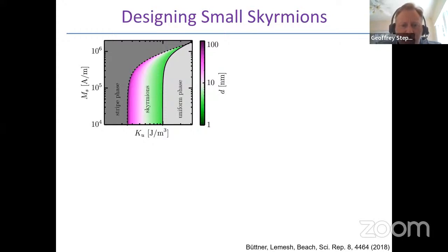So if one wants to improve the behavior and really push skyrmions down to a limit of 10 nanometers or less, that would make them desirable for applications, but also imbue them with the kinds of high-speed dynamics that would be required for high-speed manipulation, one thing that one has to do is get rid of the stray fields. And so one way to do that is by moving to multi-sublattice materials like ferrimagnets or anti-ferromagnets.